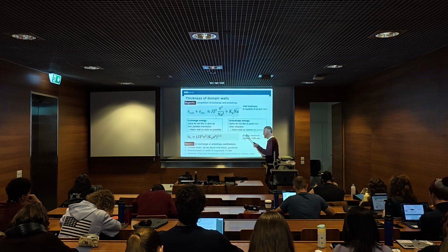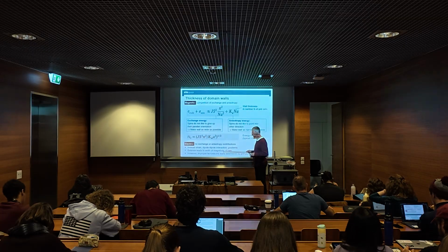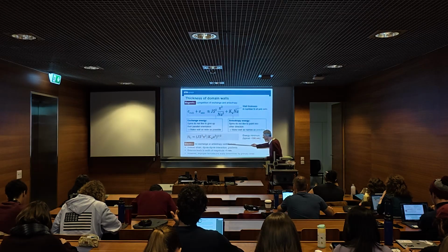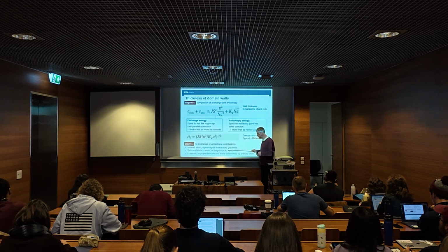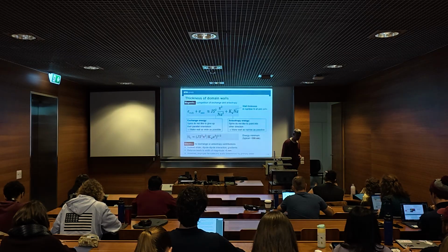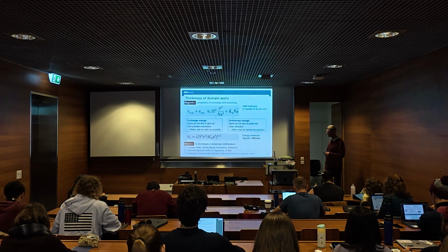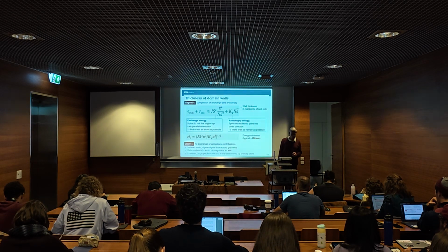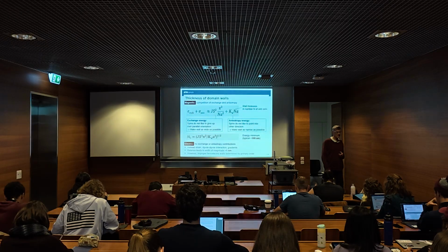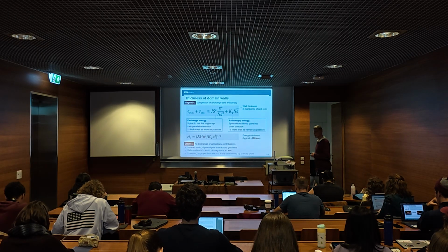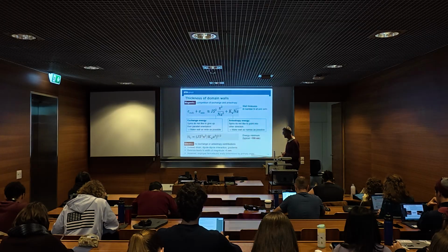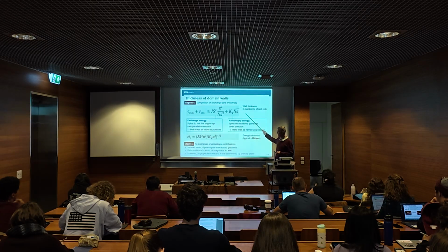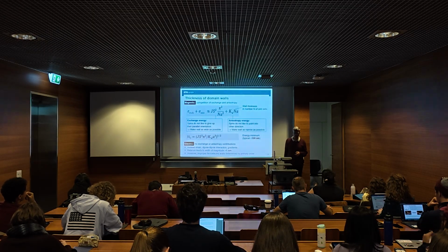But then you have dipole-dipole interaction, gradient effects, and many other effects, so that in total they tend to be very narrow. Since you have anisotropy energy, which wants narrow walls, ferroelectric walls, for that and other reasons, are typically very narrow: one unit cell or a few unit cells. Unless you have improper ferroelectric order, because then the material is primarily not ferroelectric, it's only a side effect that it's ferroelectric, but something else dominates the wall width. If you have magnetically induced ferroelectricity, then you have to look at them as magnetic domain walls, and they describe these processes by the ferroelectricity.